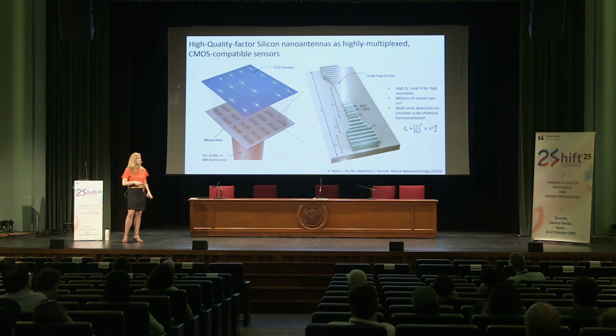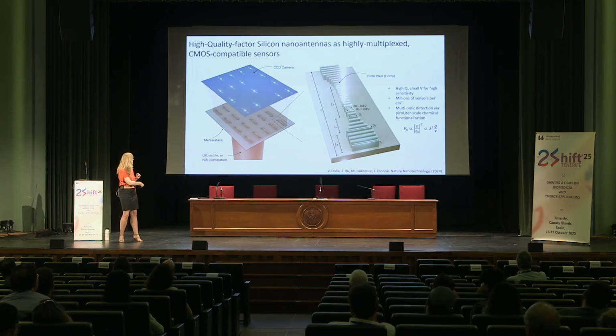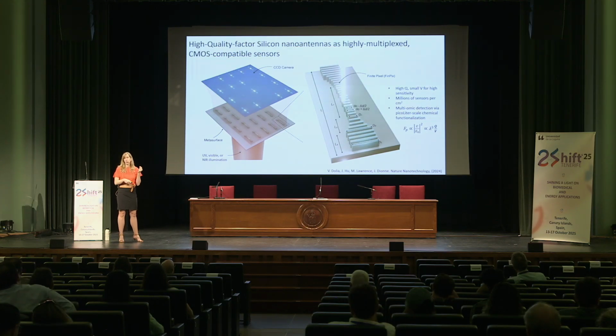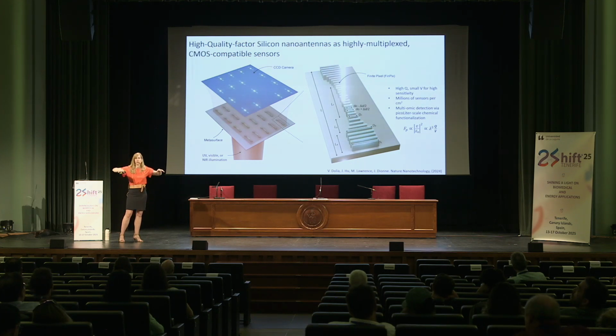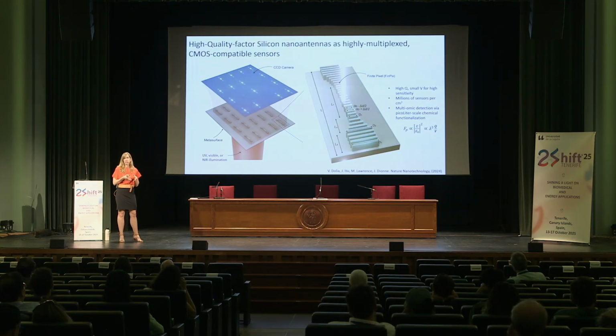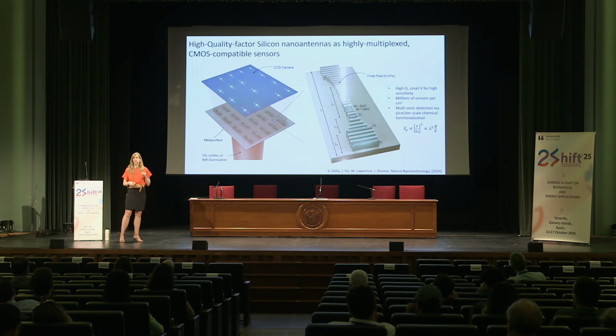So these structures are designed to have a high quality factor, meaning that light goes from the bottom, gets trapped into this almost waveguide type propagating mode for a long period of time. So quality factor is a measure of how long light gets trapped in the structure. But then the structure is also designed to confine light to extremely wavelength and sub-wavelength scale. So we have a high quality factor and a small mode volume. And based upon the size of these structures, we can actually pattern millions of these per square centimeter in the clean room. And why do you want a high quality factor and a small mode volume?